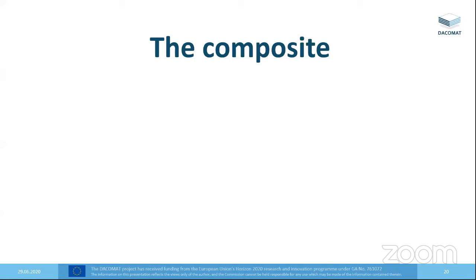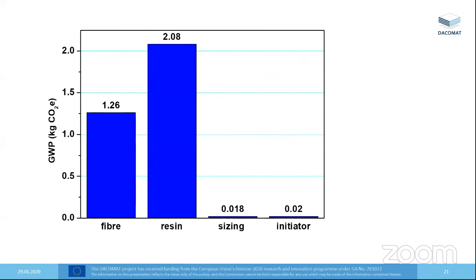Then we can offer this model as part of the decision process for when they start changing formulations. Okay, you're going to vary this amount of resin, you're going to use that initiator, you're going to use that coupling agent. What effect does that have on the overall impact of the composite? And this is what we found.